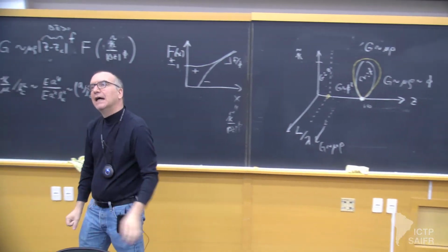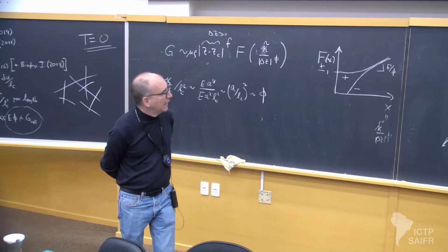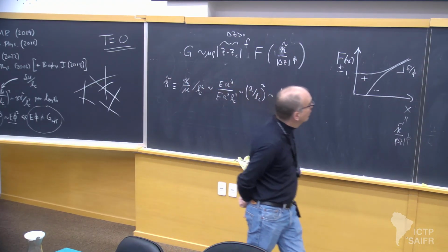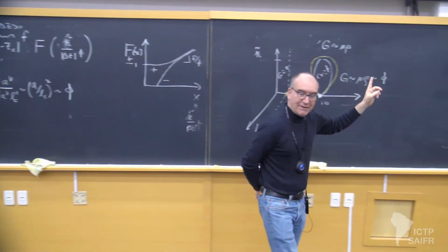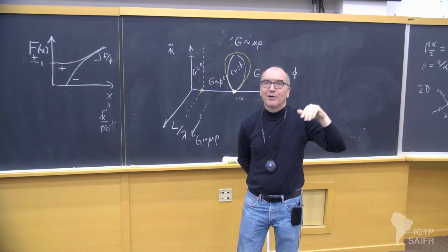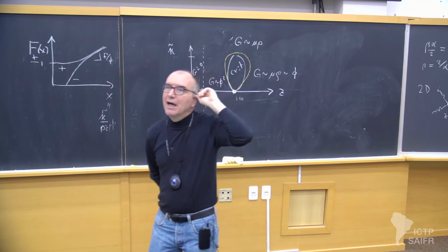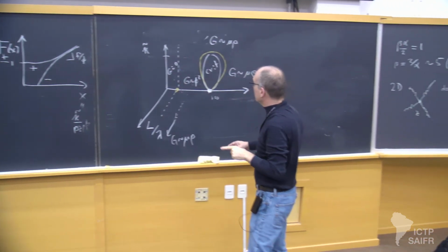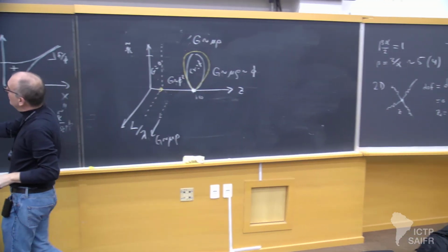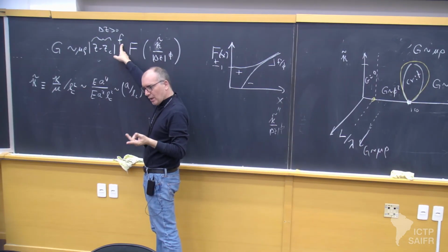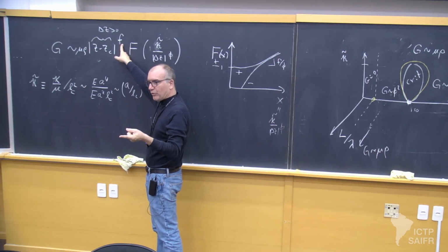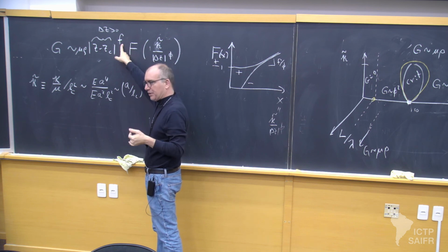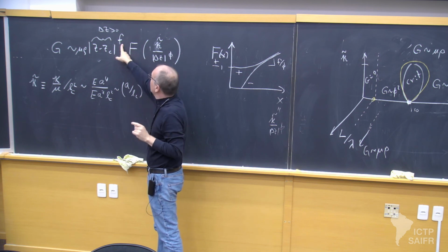But do you get similar scaling functions for the rigidity percolation? No. So in that paper, and I've forgotten the values, I have a terrible memory for numbers. What I can tell you, just because I reminded myself recently, this F exponent, mean field is 1, 2D is 1.4, plus or minus error bars, which are small compared with 0.4.